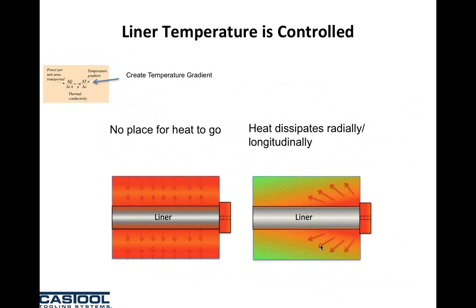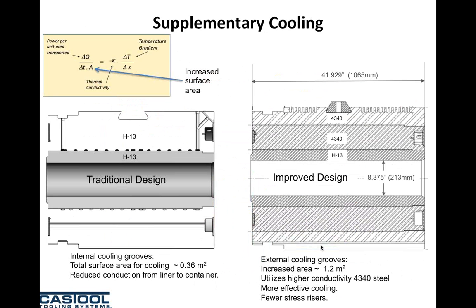There's no reason whatsoever to have the entrance of the container the same temperature as the exit. And if we provide a taper longitudinally, we allow more dissipation. So we can dissipate heat from the liner to the outside of the mantle, diametrically, and we can also dissipate it from the exit to the entrance. And sometimes for some profiles that require very high productivity, there is too much heat to dissipate by the container itself. But we can put complementary cooling on the OD of the container.